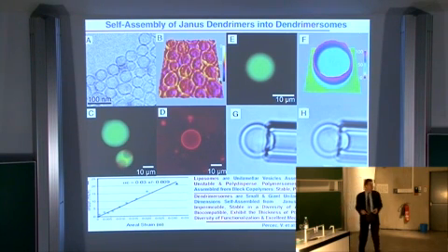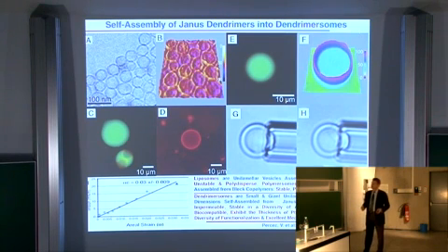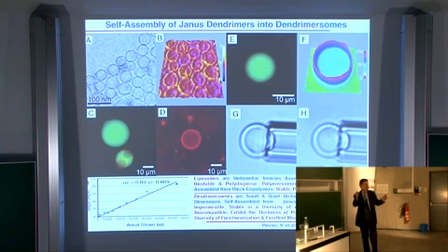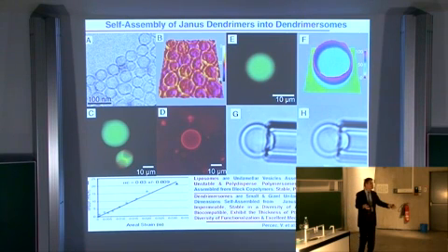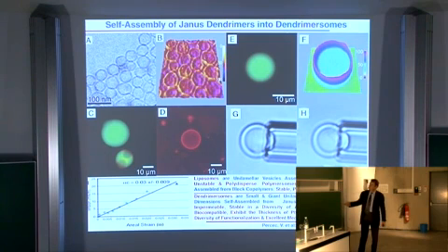Therefore, we can make structures that function and provide mimics of biological cell membranes. We can make giant vesicles that we attach to a pipette to measure the mechanical properties of this vesicle, and figure out that they are better than the mechanical properties of the commercial vesicles that are loaded with 50% cholesterol, and nobody wants to incorporate cholesterol in their own body, but all the delivery of drugs is generated by these vesicles.